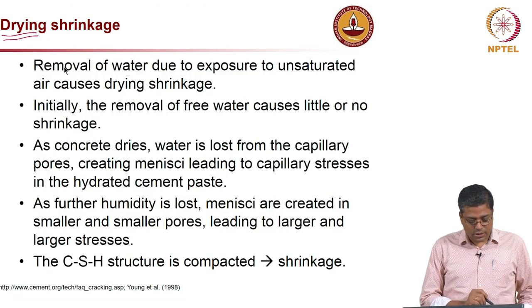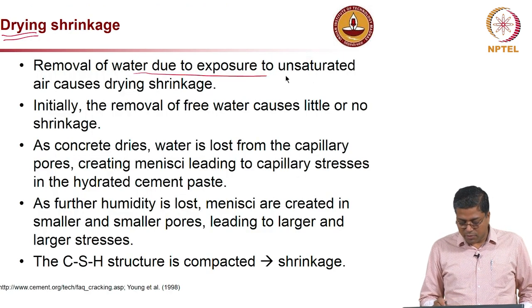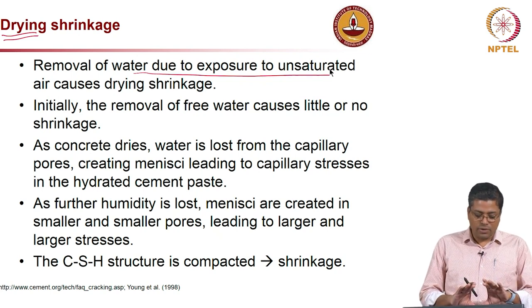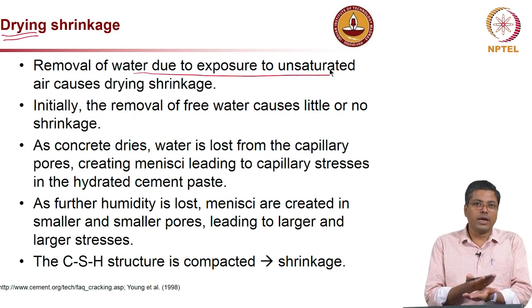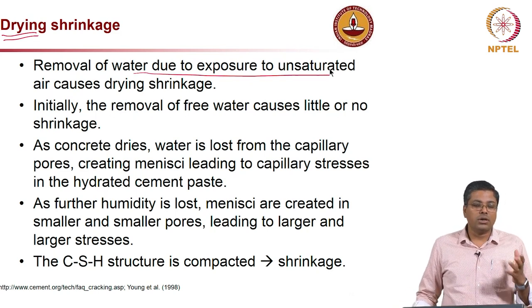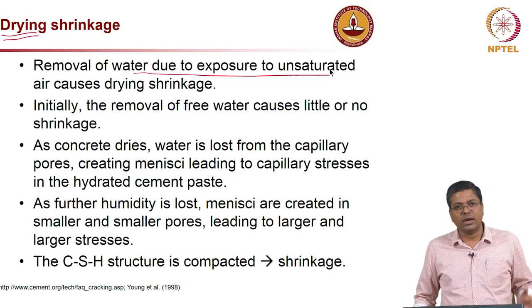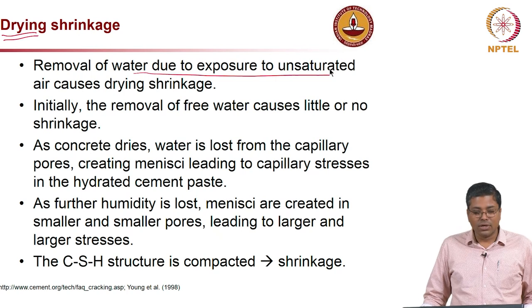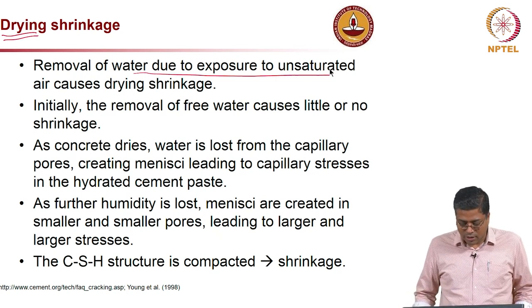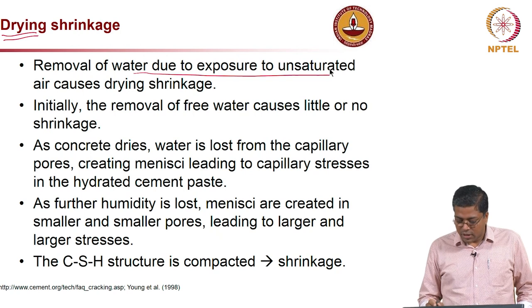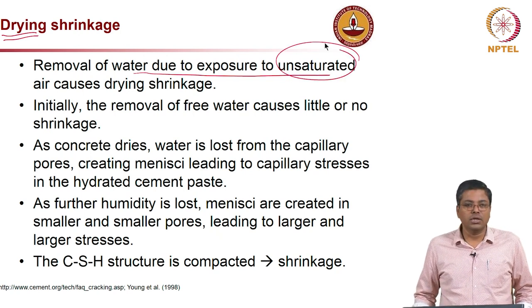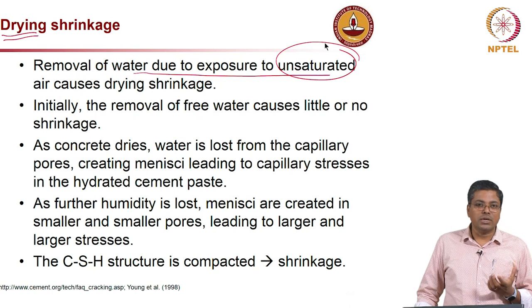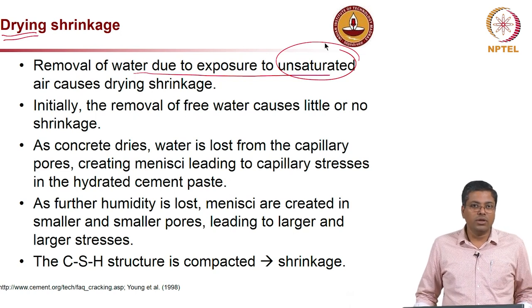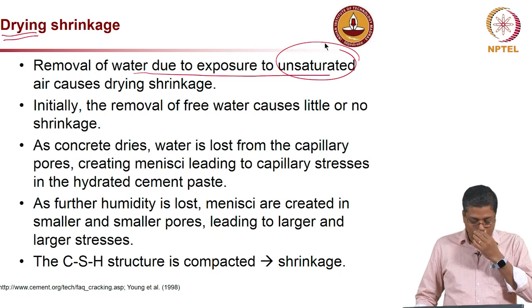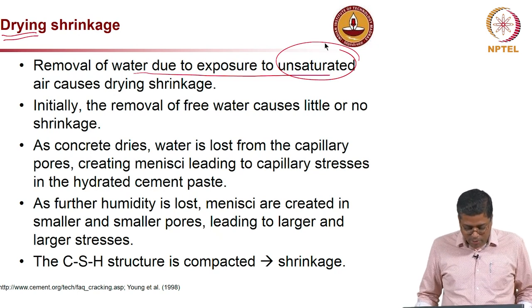We could see that during the hardened state, mainly removal of water due to exposure to unsaturated air. What it means is, if you have a hardened concrete and the air right above the concrete surface does not have sufficient humidity, or it is in a relatively dry environment, not really humid, that is what is meant by unsaturated condition. So, what will happen? The water which is present inside the concrete will try to diffuse outward and get into the environment outside, or drying happens.